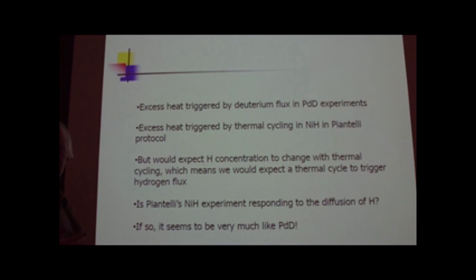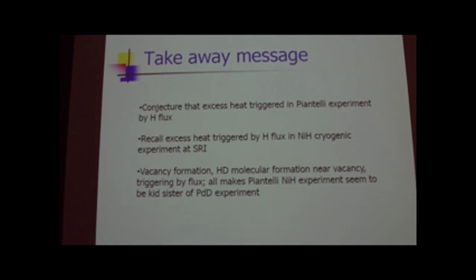Note that pressure cycling is also observed to kick on an excess heat event in nickel hydride, which would have the same effect. You raise the pressure, more hydrogen comes in, you lower the pressure, hydrogen goes out. That's a way to induce a hydrogen flux. So the issue: is Piantelli's nickel hydrogen experiment responding to hydrogen diffusion? Well, it sure looks like it. And if so, then it's looking to me like the kid sister of palladium deuteride. The takeaway message is that the Piantelli protocol under these interpretations looks like it's doing what the current ramp protocol is doing in the Fleischmann Pons experiment.